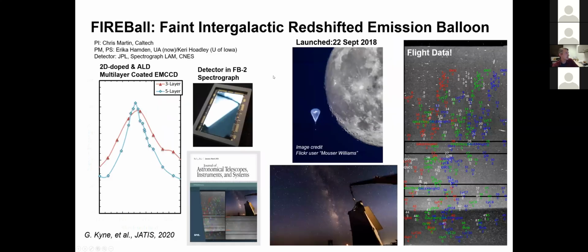So here's the results of some of that work. I lost the axes here, but these are the measured detector quantum efficiencies for the detectors delivered to the Fireball instrument, with peak quantum efficiencies in excess of 80% centered at this 200 nanometer wavelength range. Here's an image of the detector installed in the spectrograph and some of the flight data that was obtained in the last launch of Fireball.